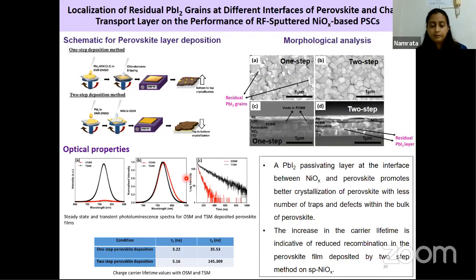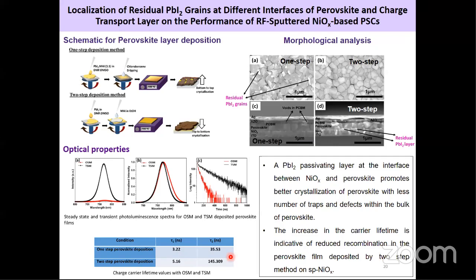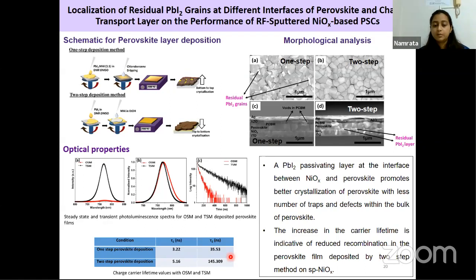When we normalize the spectra, we can see that there is a slight blue shift in the PL peak for the two-step method, and a blue shift again corresponds to a reduced number of defect sites. And when we further took the time-resolved photoluminescence, we observe that the lifetime for the two-step method deposited perovskite is much higher compared to the perovskite deposited by one step. So an increased lifetime suggests that recombinations reduced in the bulk of the perovskite. So in total, we can say that with the two-step deposition method, we have a better perovskite crystallinity.